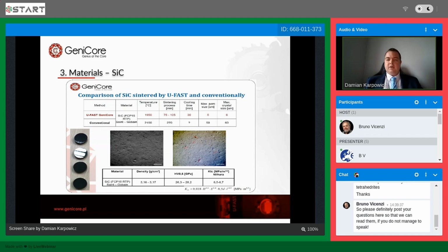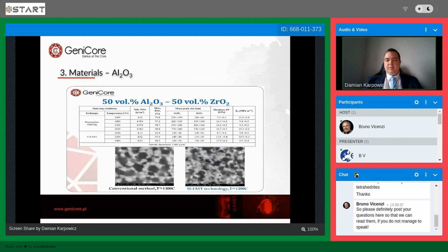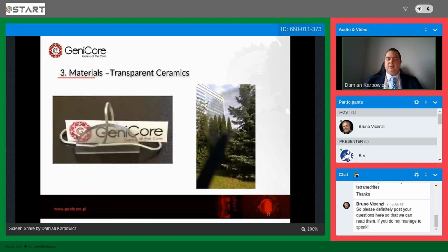And this is literally because we are heating the powder directly. The cooling time, unfortunately, we didn't have a comparison to the conventional method. Nevertheless, I think we can easily assume it was also shorter because we use an advanced cooling system for the stamps, and the pore size and crystal size are also smaller. When it comes to limiting the grain growth, I think this alumina can be a great example because with the naked eye we can see the difference: the conventional method on the left side and UFast technology on the right side. So this is the phenomenon which can increase the quality of our materials.